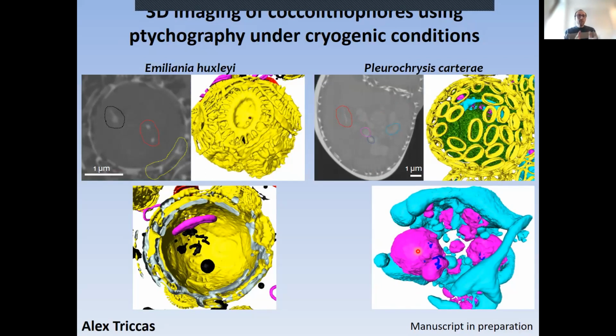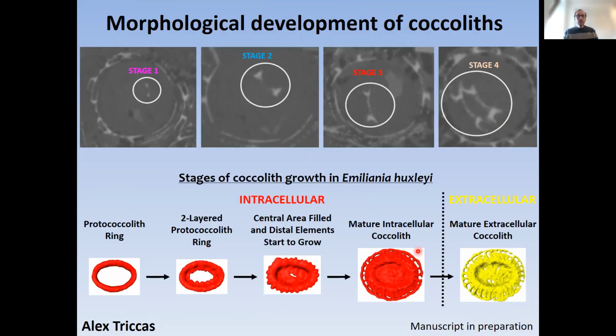So I'm going to focus now only on Emiliania. I won't talk about Pleurochrysis, but the data is actually very similar. The way that they made the cells is that we had to load them into a glass capillary, freeze them using a plunge freezer, and then they are analyzed frozen at the synchrotron. So everything here is cryopreserved. In the capillary, we just have a very large number of cells and have the 3D reconstruction of all of them. So basically, it enables us also to do some statistics, actually.